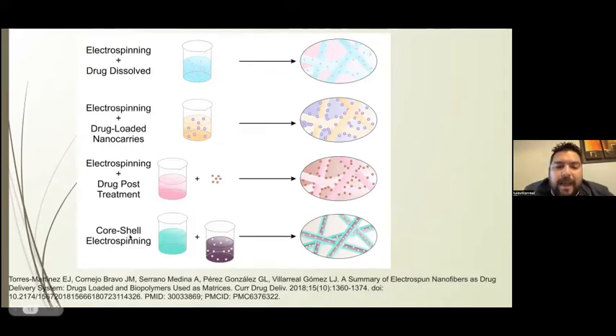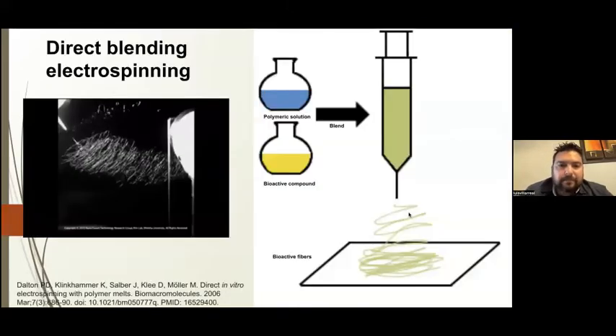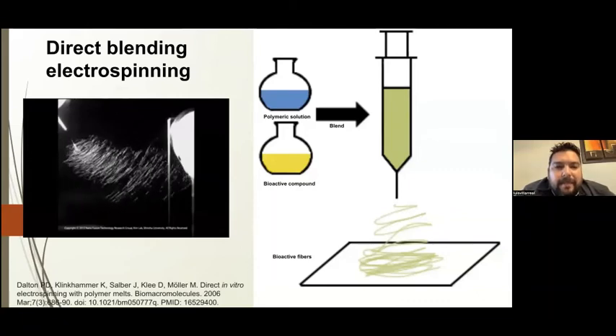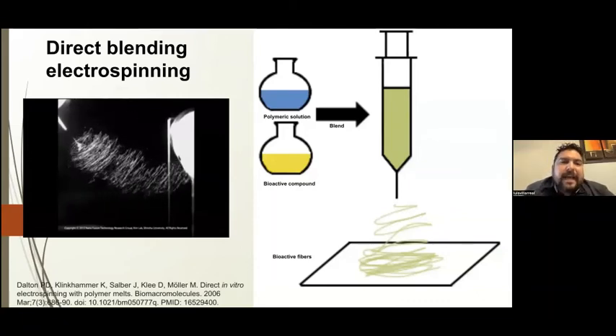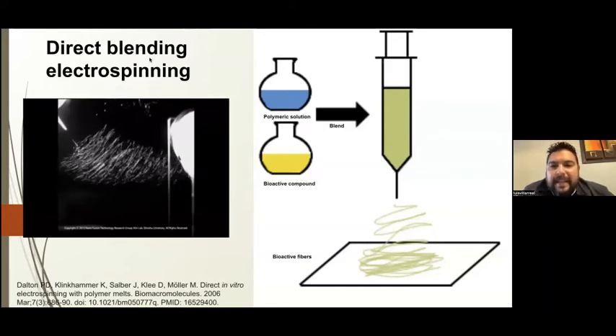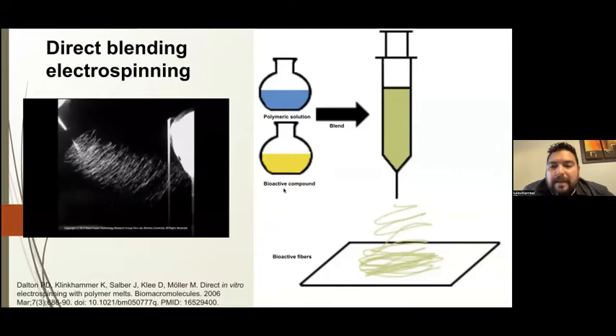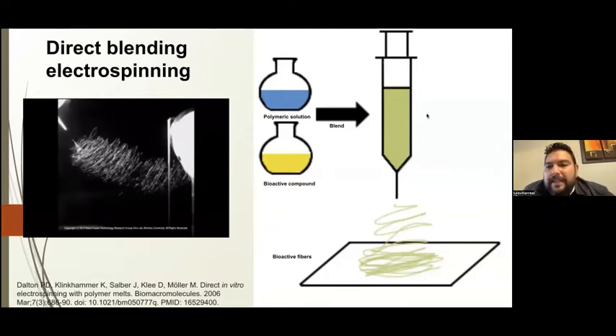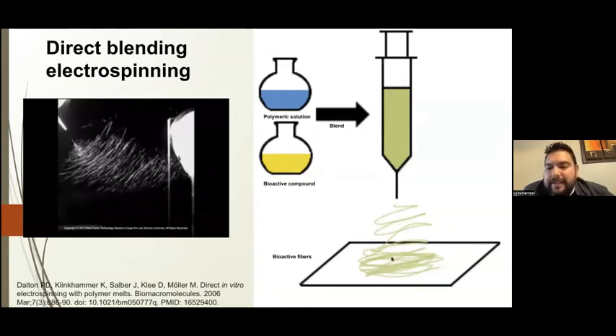Or there is coaxial electrospinning, where you have core-shell fibers, and you can put labile proteins, for example, or living cells into the fibers. There are some reports that researchers in France have electrospun living mammalian cells into fibers, and they checked the viability after the process. To have bioactive molecules between fibers, there is direct blending electrospinning. This is a very easy technique where you put the bioactive compound solution into the polymeric solution and then run the electrospinning process and create the fibers.